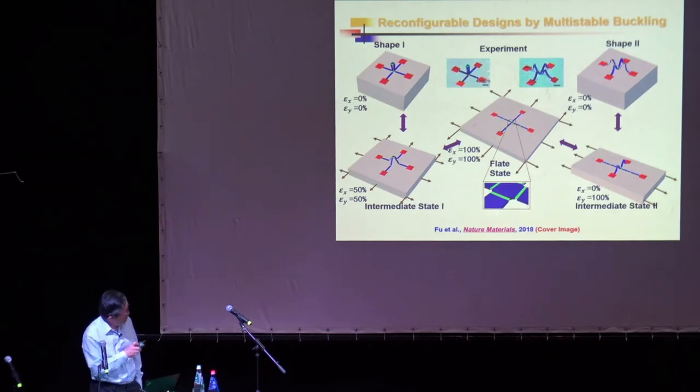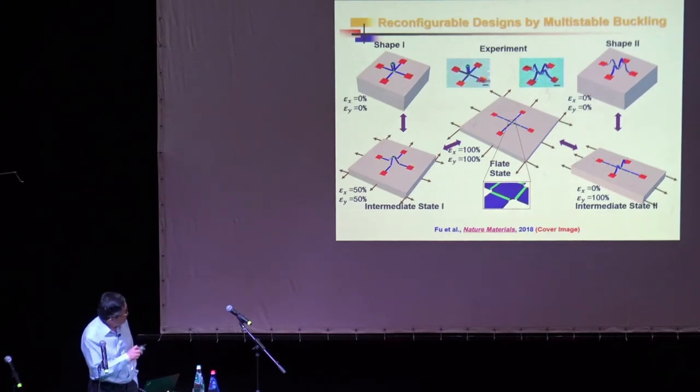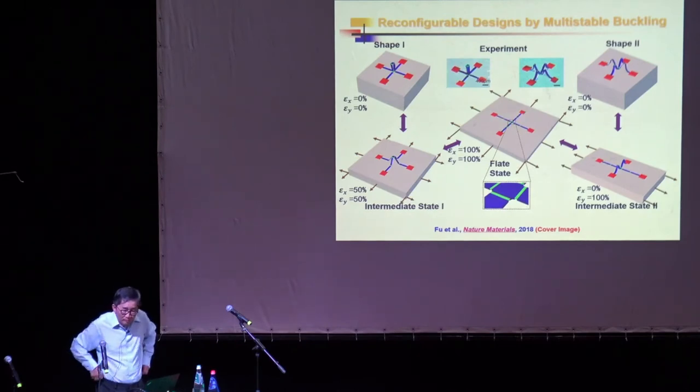And in addition, you see the green color. What is the green color? That is the location where we put the same material but with reduced thickness, where we want the hinge to form. So now you can see this structure here. Once the pre-strain is relaxed, the bonding sites like to shrink, the spacing between the ribbons becomes smaller, and the structure likes to pop up.